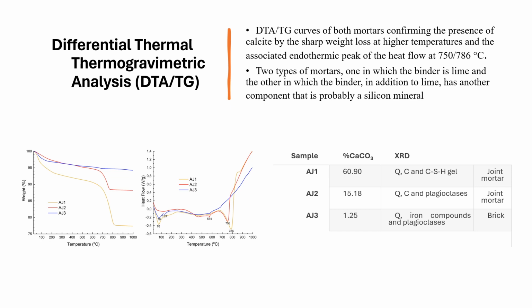DTA/TG curves of both mortars confirm the presence of calcite by the sharp weight loss at higher temperatures and the associated endothermic peak of the heat flow at 750/786 Celsius. We have two types of mortars, one in which the binder is lime and the other in which the binder, in addition to lime, has another component that is probably a silicon mineral.